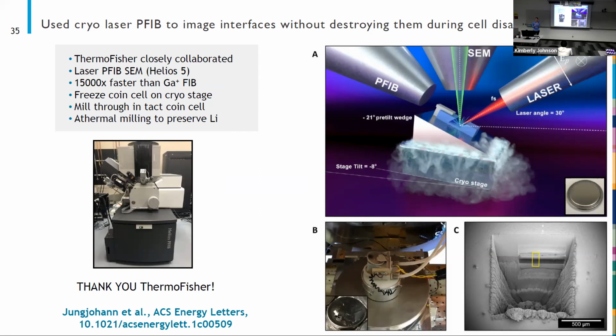So Katie had this idea that maybe Thermo Fisher would be willing to put a cryo stage on this instrument, and maybe we could take a coin cell up there and see if we could just mill through the entire thing. It's necessary to freeze the cell. If you don't, then the electrolyte will just evaporate and muck up your system and cause all sorts of problems, including short circuits while you're milling, because you need your electrolyte to be frozen so you're not short circuiting your cell with the milling process.